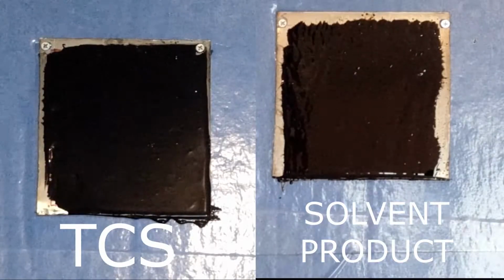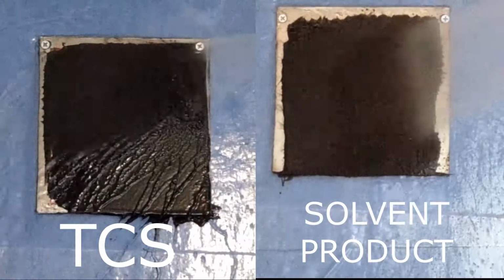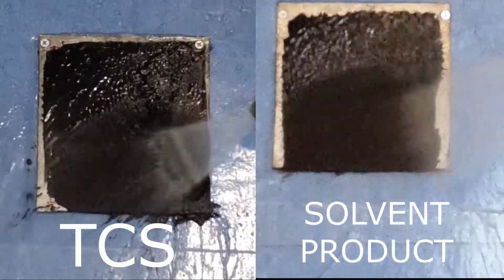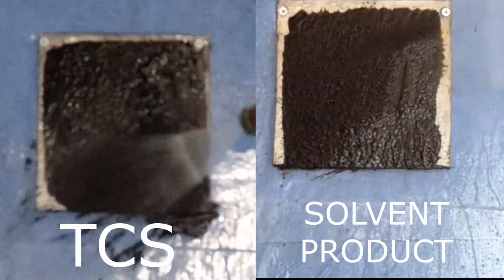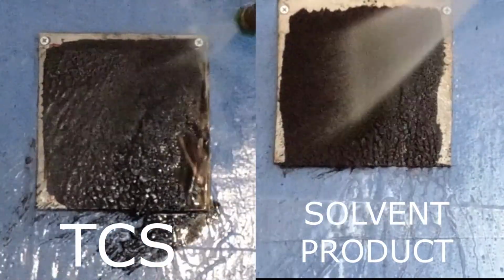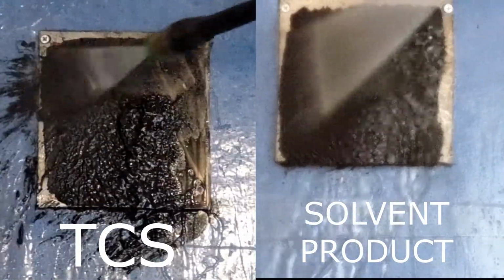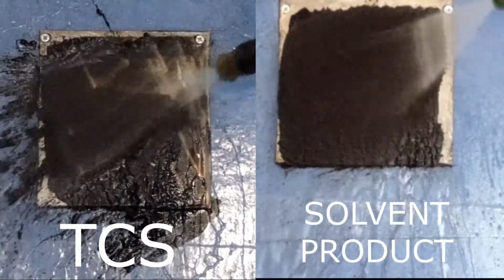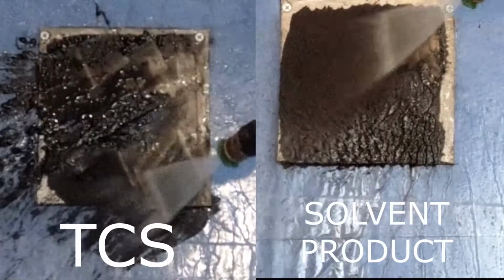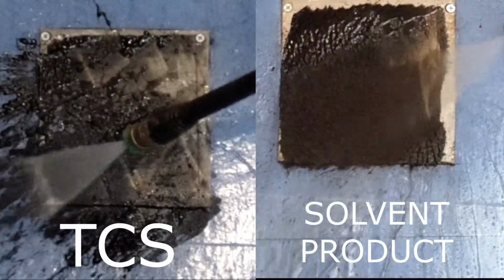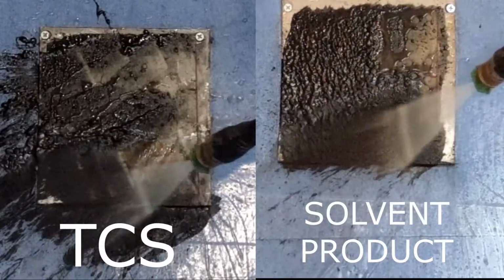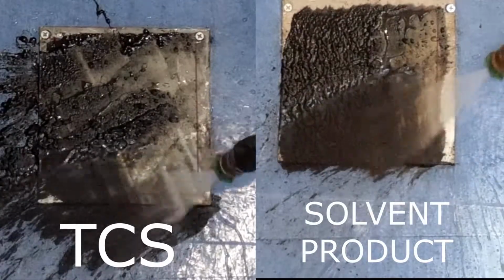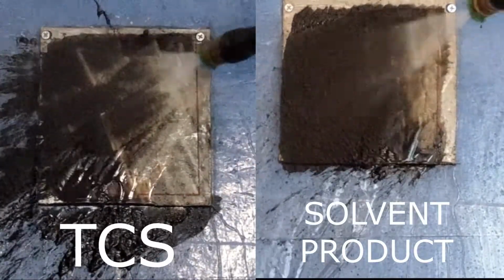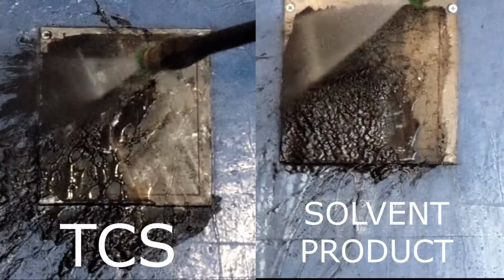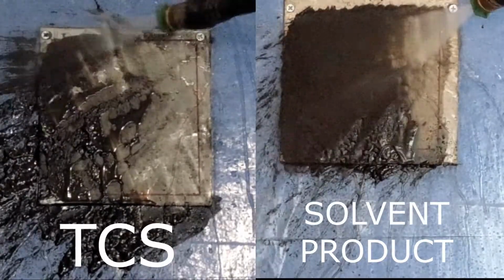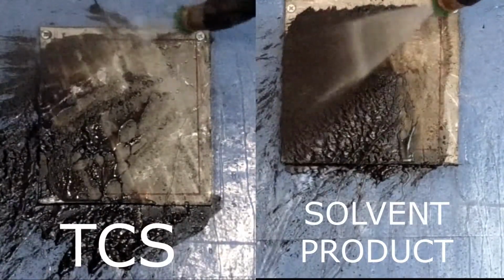The video is now of the removal of the asphaltene samples using a 1800 psi pressure washer. You'll notice on the solvent that even though there is a small amount of removal, the water must first remove the remaining excess solvent prior to the asphaltene, and you'll see the difference with the TCS slide. Both samples were prepared by heating the asphaltene to a temperature of 165 degrees Fahrenheit for a period of 60 minutes to allow the polymers to adhere more firmly to the steel section.